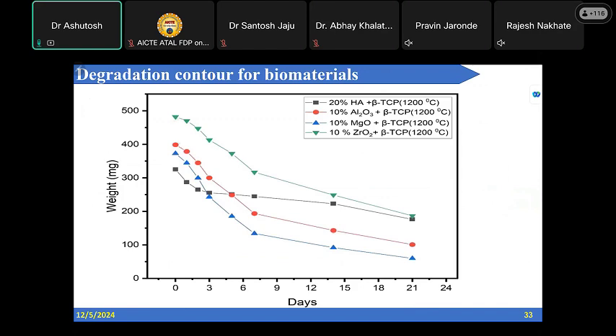So in case of the zirconia and beta TCP, this is the weight at 0 day. And after the 21 days, what is the weight? So you can find out that I am getting good degradation in case of this magnesium oxide, where it has a good degradation after 21 days, followed by Al2O3, then followed by HA, and then zirconia.